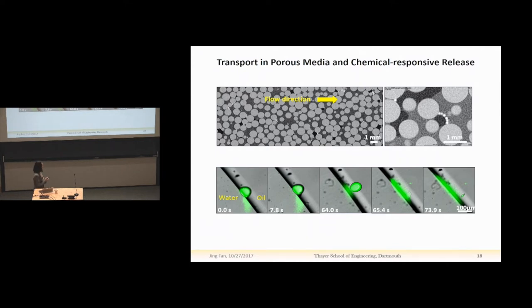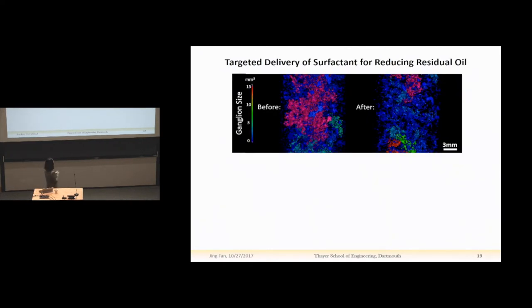And finally, the most important step is to evaluate the oil recovery efficacy of these capsules. Again, we construct the model porous media and saturate it with oil, inject water to have some residual oil, and then we use micro-CT again to scan the whole sample to get the structure of all the residual oil. And here we use different colors to represent different sizes of the oil ganglia. For example, all the ganglia with a size between 0 and 15 cubic millimeters have a color from blue to red. And any ganglia larger than 15 cubic millimeters will have the color pink. So here you see all the pink ganglia, a couple of very big oil ganglia trapped there. This is after water flooding.